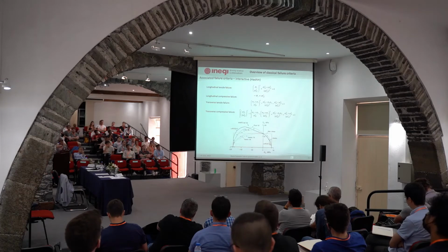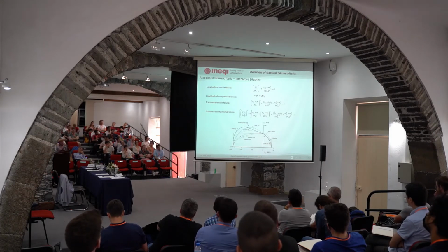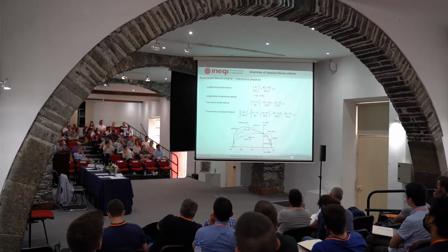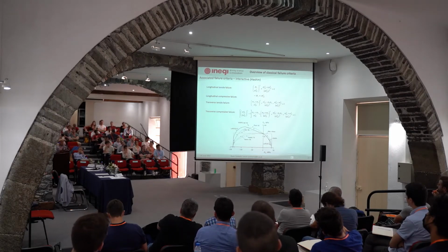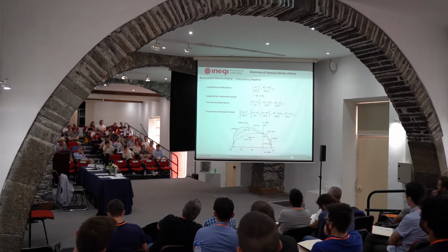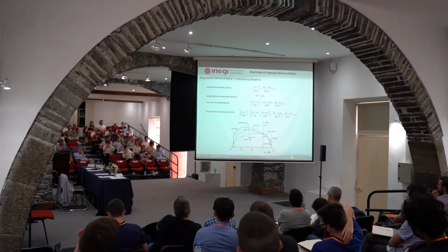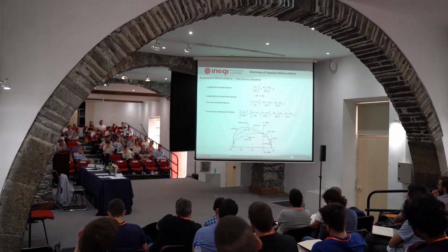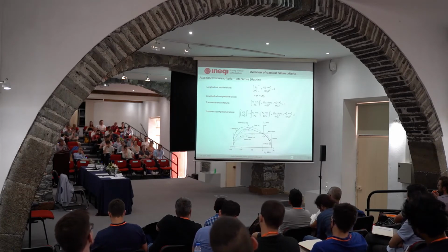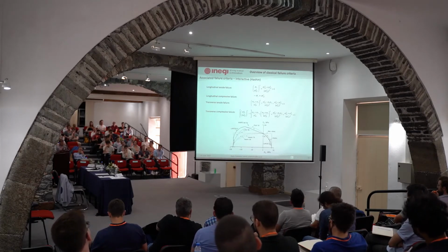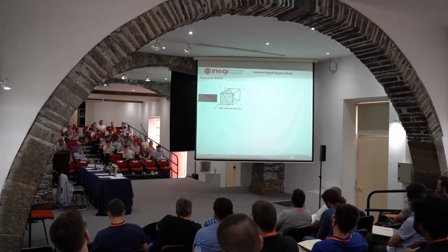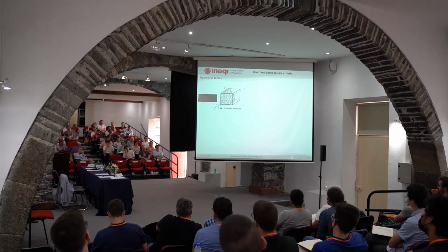And Hashin, again, you can see that cannot capture this effect. So again, transverse tension and compression versus shear strength. You have experimental points, and Hashin cannot capture this effect over there. So you could argue, okay, it's not a problem because it's conservative, but you're going to over-design a composite structure.